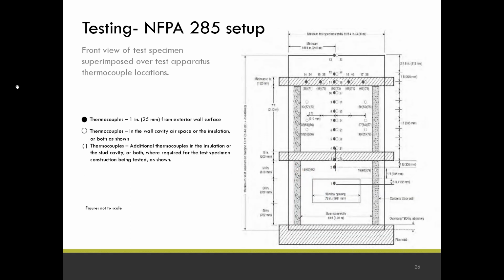You look at this from the front. It is instrumented with a large number of thermocouples. Basically, they go up the center, they go across the top, 10 foot above the top of the window, and this doesn't really show up. They also come down both sides. So basically, you have this window in the middle, a fire starts in the room below.